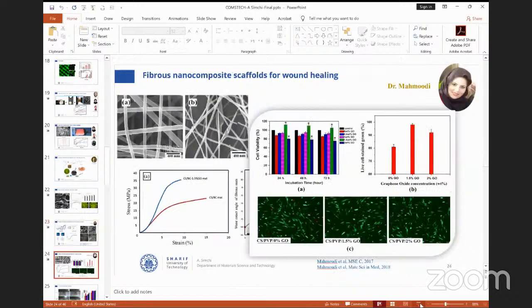The other area which I would like to mention is wound healing. There is a lot of activity for preparing materials and using nanomaterials for skin regeneration and wound healing. Without any doubt, fibrous materials are very important because the permeability of the scaffolds is very important. The size of the pores is very important, and the mechanical properties are very important. At the start, we made some nanocomposites by mixing graphene oxide and graphene nano layers with polymeric materials, mostly chitosan, because chitosan is a natural biopolymer with antimicrobial activity.